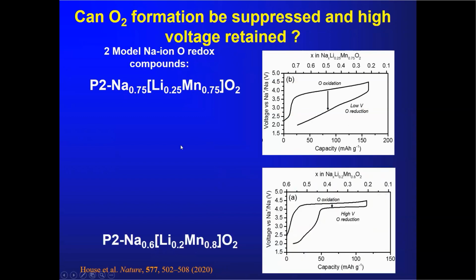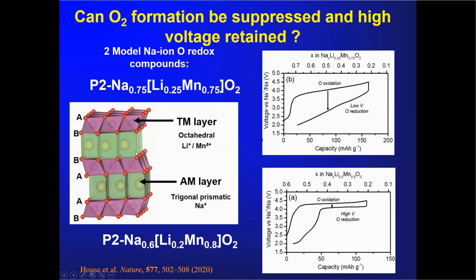So what you're seeing here are two compounds, so-called P2 structure. That's because when you have sodium in the alkali metal layers, it prefers trigonal prismatic coordination. So this is the layered structure we have now. We still have transition metal ions, of course, in octahedral sites, but we now have sodiums, the larger sodiums, in these trigonal prismatic sites. But the point here is these two compounds have the same crystal structure, very similar composition.